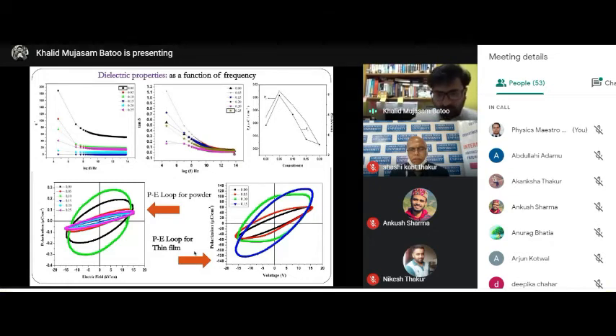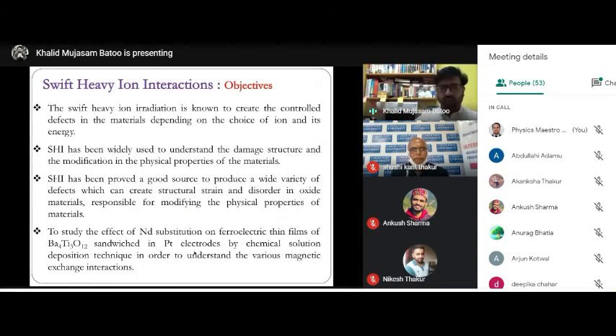What we did was change the experiment further by using swift heavy ion irradiation. It's a very good technique to create defects or damages in a material in a controlled fashion, which helps change the structure and tune the properties of the material.